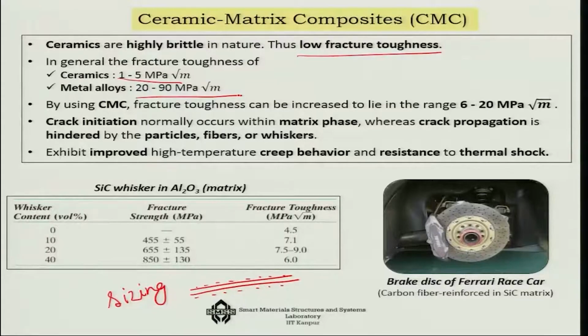So when you will be using CMC, your target will be to lie, as far as the fracture toughness is concerned, in the area of 6 to 20 megapascal root meter. Now the crack initiation normally occurs within the matrix, whereas crack propagation is generally hindered by the particles, fibers or whiskers inside the matrix, which will stop the growth of the crack, and it exhibits improved high temperature creep behavior and resistance to thermal shock. So these are some of the very good characteristics of ceramic matrix composites.